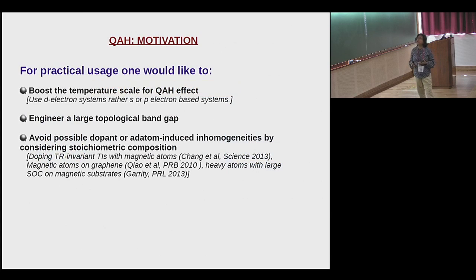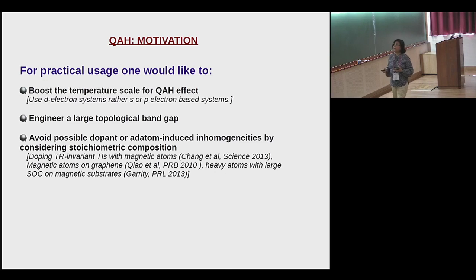So the motivation, given this interest in quantum anomalous Hall, for practical use, one would like to boost the temperature scale of the topological anomalous Hall, as I mentioned, and therefore use d electrons rather than the conventionally used s and p electron based systems. Engineer a large topological band gap, and avoid possible dopant or add-atom induced inhomogeneities, like the original suggestions or the experiment where one doped the topological insulators with magnetic atoms, or put magnetic atoms on graphene, or put heavy atoms with large spin orbit coupling on a magnetic substrate. All of them were either add-atom physics or doping induced, which may lead to inhomogeneities in the system. So it's better if we can have it in a stoichiometric material.